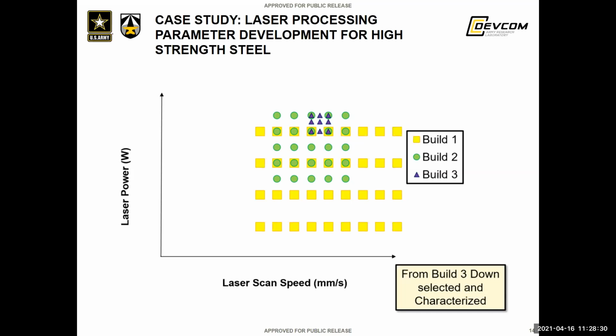And then with this, now that we know that this is theoretically weldable as a single layer, we look at the effect of laser scan speed and power. We generate basically a design of experiments, but I like to add more because it's not one or nothing. It basically needs an in-between. And we try to look at a process window. This process window is basically where we can build that we think will have a high enough critical density that will have the mechanical properties required to fulfill our project.